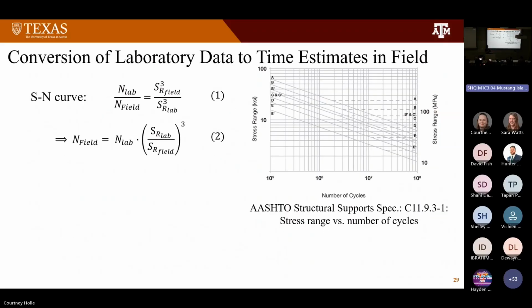This slide shows how we convert our lab data to field performance by using the SN curve. The SN curve on the right shows the relationship between the stress range and the number of cycles. The x-axis of this chart represents the number of cycles, and the y-axis represents the stress range. These different lines represent the different detail categories from the AASHTO fatigue design curve. Here we can see that as the stress range decreases, the number of cycles increases. So the equation on the left from the SN curve shows the number of cycles is related to the stress range to the third power.